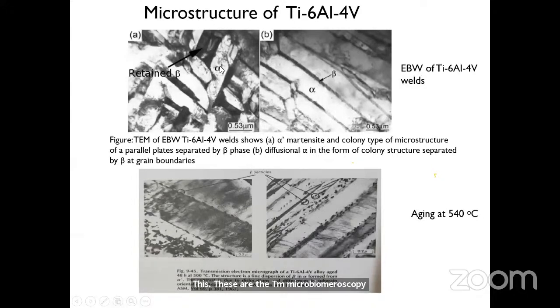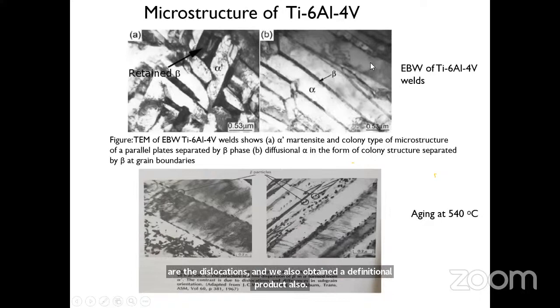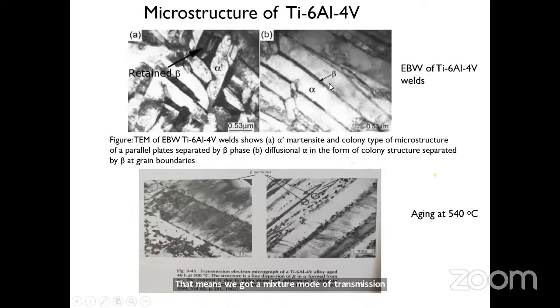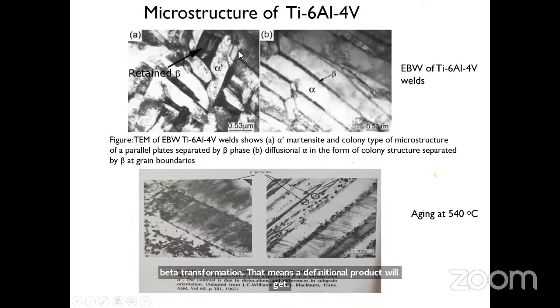Here you can see the alpha prime martensite in a zigzag fashion. And also you can see the lines present here. These are the dislocations. And we also obtained diffusional product. That means we got a mixed mode of transformation. So the initial transformation is alpha beta transformation. That means a diffusional product you will get, which is then interrupted by martensitic transformation.